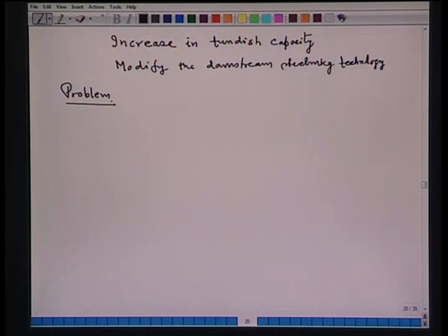in the same length of the mold and for the same cooling rate, more amount of steel is available in the mold. So, it has to be solidified, so that a partially solidified strain is withdrawn from the bottom of the mold. Now, the quantity of steel has become more. How can the same amount of cooling and same technological gadgets which have been provided on the mold in the conventional slab caster meet that requirement? That has to be thought.